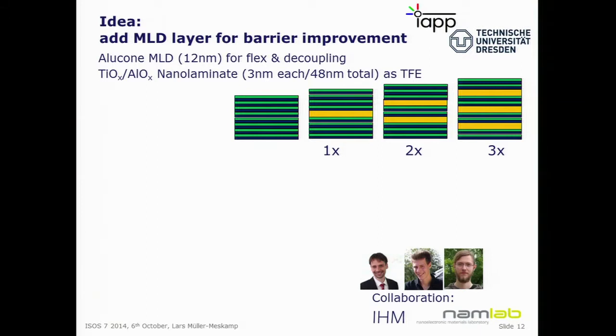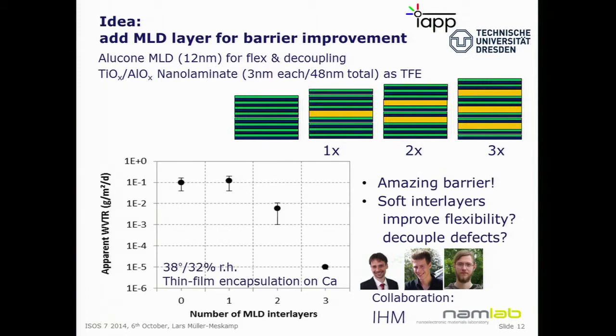Then we insert a 12 nanometer alucone. We insert 2 12 nanometer alucone layers, and we insert 3 12 nanometer alucone layers. Okay. If we measure this, it looks pretty cool because we have a very poor barrier for no MLD layers, but for more MLD layers, the barrier goes down a lot. So 1 times 10 to the minus 5, that's already a pretty cool value, even at these conditions.